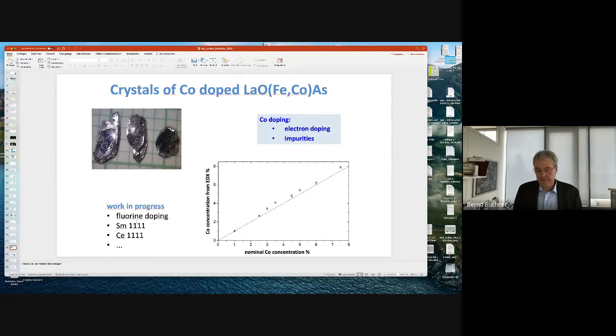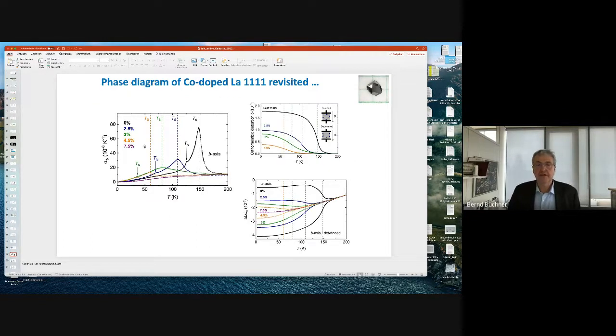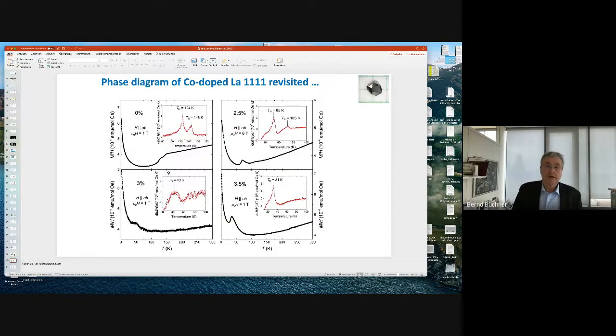So let's have a look at this. So we can now revisit the phase diagram. We can do all these measurements. So we can use dilatometry to measure the structural phase transitions. So you see the orthorhombic splitting. It's large for the parent compound, becomes smaller upon doping. We can also follow the structural phase transition from thermal expansion measurements. We can measure the magnetic susceptibility.